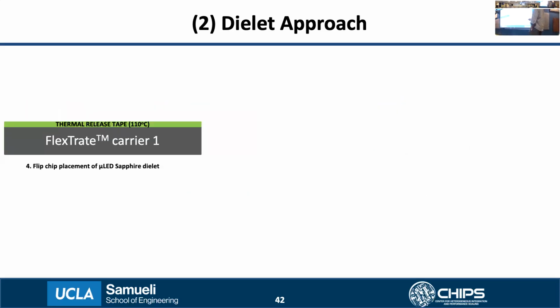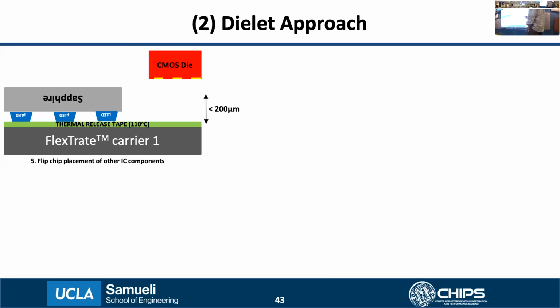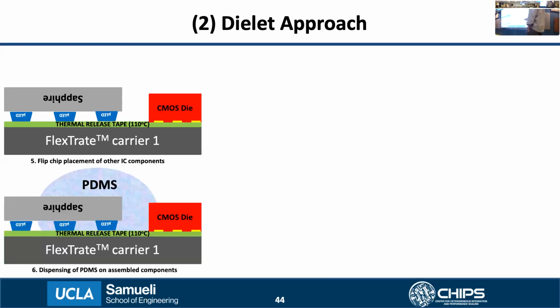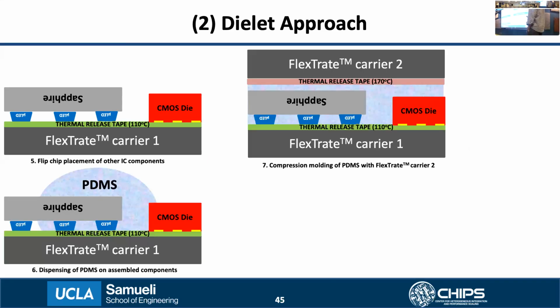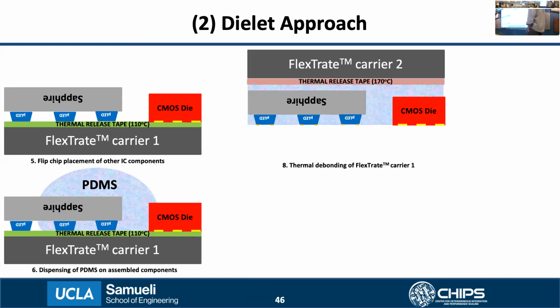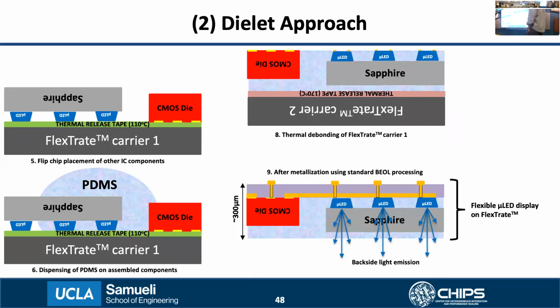Now this is a repetition of the FlexTrate process. We have the tape, and then we flip-chip place this sapphire dielet with the LEDs. But this time the sapphire is not detached from the devices, and it exists as part of the final substrate. Then we can place the other components as well, then do the dispensing of PDMS, compression molding, metallization, and final thermal debond.